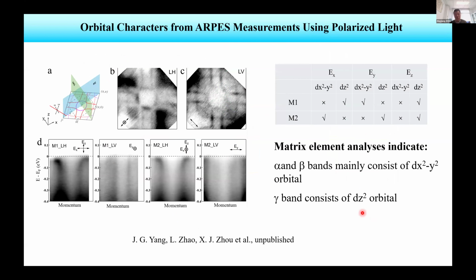Also, to determine the orbital character, we performed some polarization dependent ARPES measurements. We use different polarizations, like the E vector going this way, and also some perpendicular E vector components. So we map the Fermi surface, and we also get the band structure in different polarization geometries. By analyzing whether some orbitals are allowed or forbidden for a particular E vector, we can determine the orbital character of the observed Fermi surface sheets.